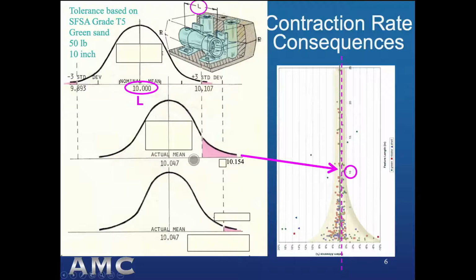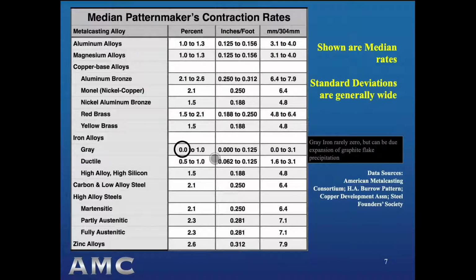So consequently, some of the castings are outside of specification, not because the process wasn't capable, but because the dimension wasn't centered because we missed our pattern maker's contraction guess. So pattern maker's contraction rate is a guess made by the mold cavity tooling builder, and the data shows why that guess is problematic, and it shows why dimensions are so difficult to achieve correctly in the first article inspection. But that data with all the variation was just for one metal alloy family, the carbon and low alloy steels.